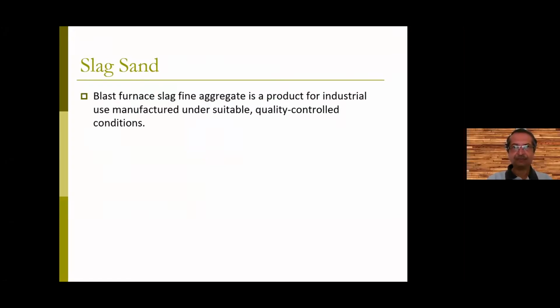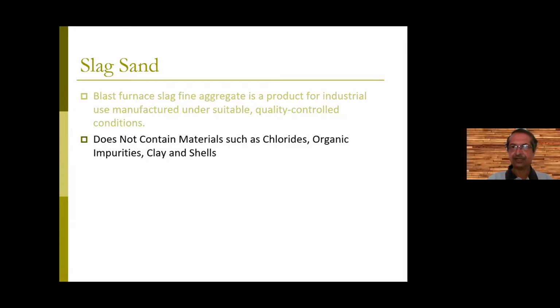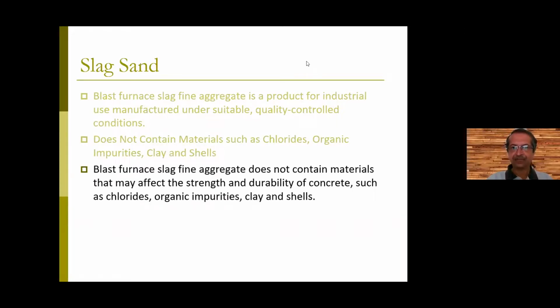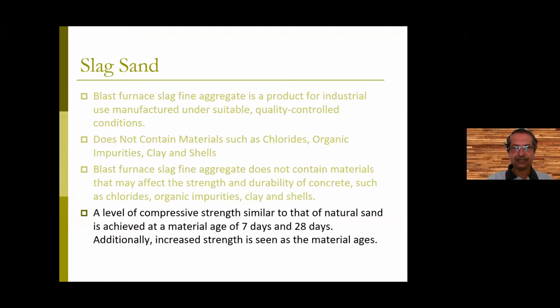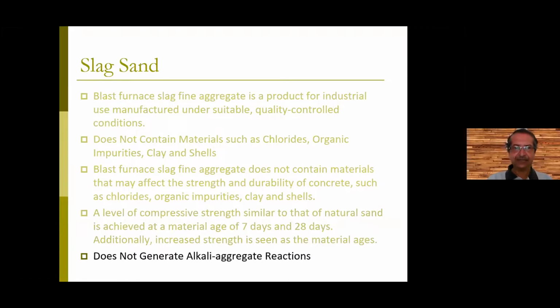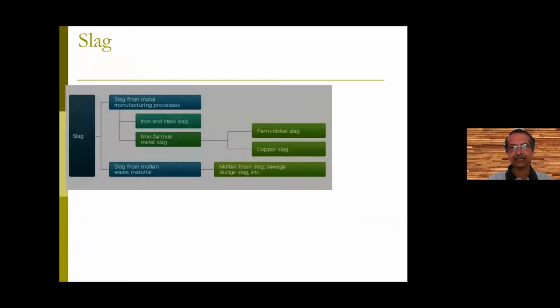So this particular one is a very suitable material because it is controlled in quality in a factory atmosphere. It does not contain materials like chlorides, organic impurities, etc. Blast furnace slag fine aggregate does not contain materials which may affect the strength and durability of concrete. The level of compressive strength similar to that of natural sand is achieved at the age of 7 days and 28 days. And it also does not generate alkali aggregate reactions.